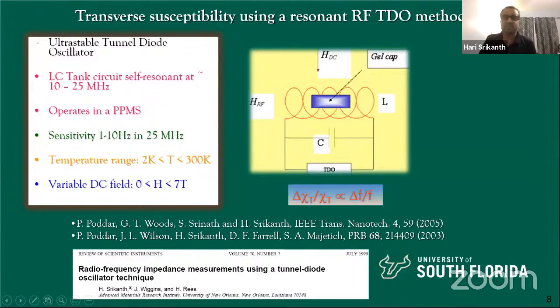And there's a reason why we do it transverse. By transverse, you look at this one right here, the DC field is perpendicular to a small RF field on the sample, making it a perpendicular geometry. The transverse geometry is not necessarily very unique because that's exactly what is used in FMR measurements or even in NMR, nuclear magnetic resonance, which involves a DC field and a perpendicular high frequency RF field, okay? So it's very similar to those techniques, and we can extract the transverse susceptibility or the change in transverse susceptibility.